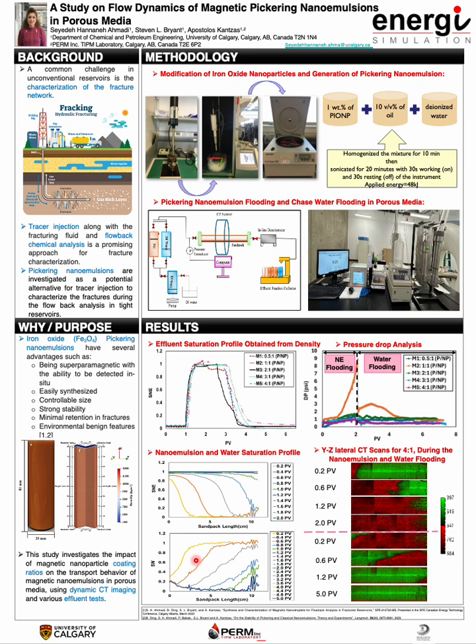The saturation profiles during the nanoemulsion flooding and post-water flooding are uniform. As you can see here, this pattern reflects the progression of the nanoemulsion front as it displaces the initial water phase, confirming the effectiveness of the injection process in fully saturating the sandpack with the nanoemulsion. During the nanoemulsion flooding process, the nanoemulsion concentration increased in the sandpack. The migration front dispersed through the pores, penetrating deeper into the medium. The nanoemulsion exhibited a piston-like movement along the sandpack, resulting in full saturation after 1.4 pore volumes of injection.